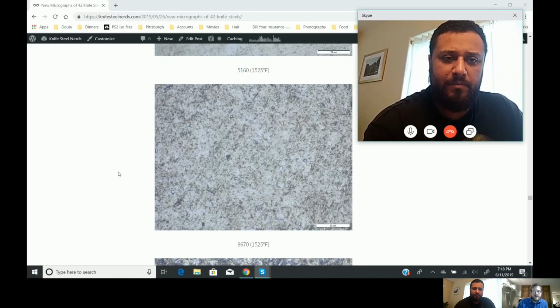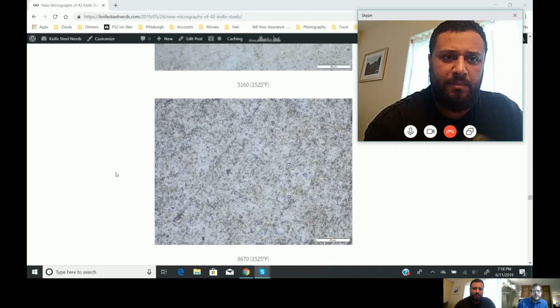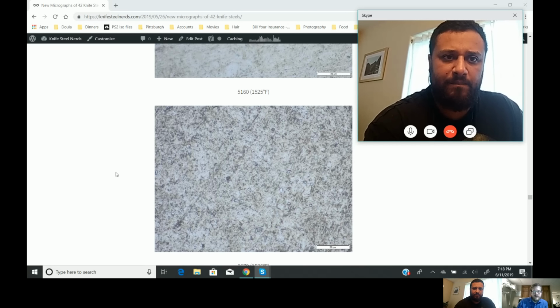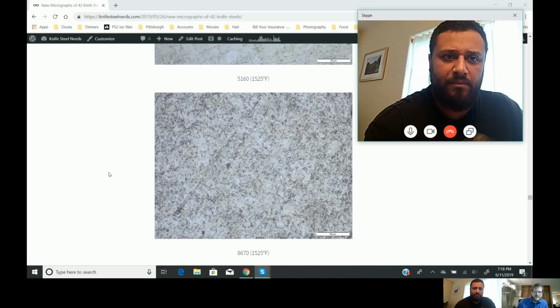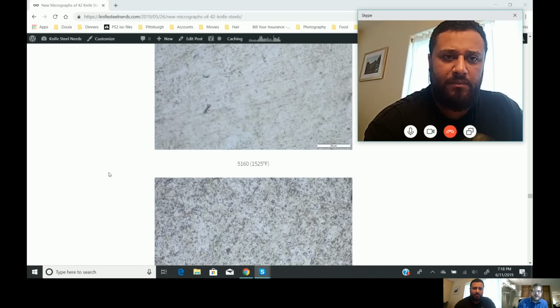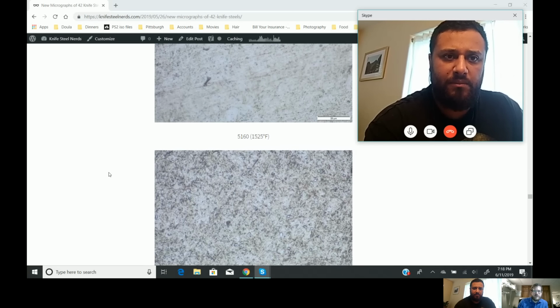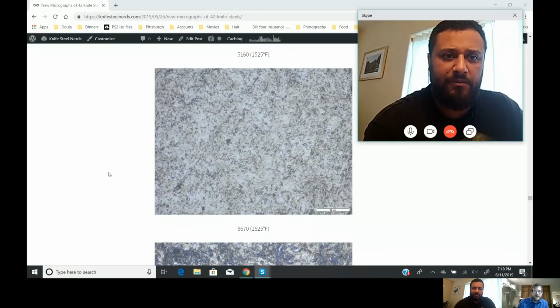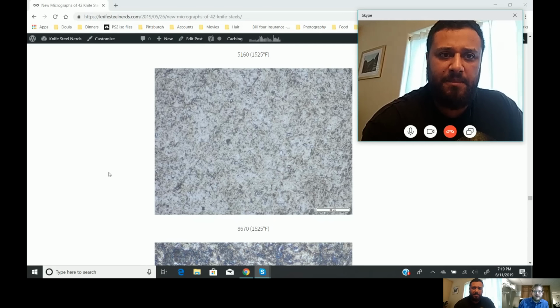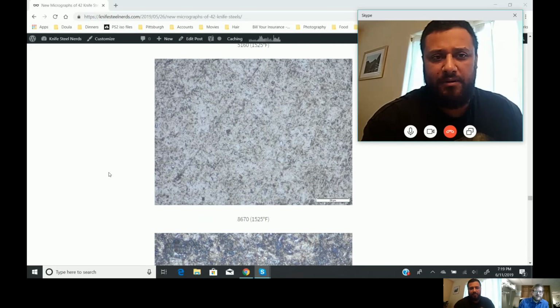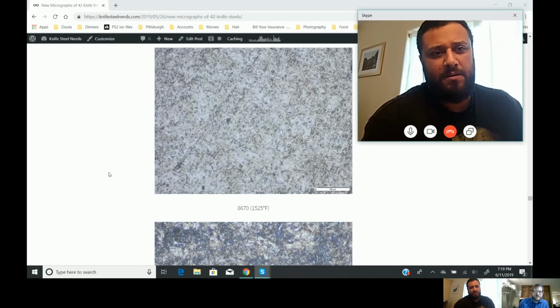They're at least a micron in size, but not big enough to really impact the toughness that much. So it's got a tiny bit of carbide, so maybe it's got a wear resistance improvement over 5160, while also being able to get a little bit harder and similar toughness. So it looks like a good choice for forging guys that want a high toughness steel.